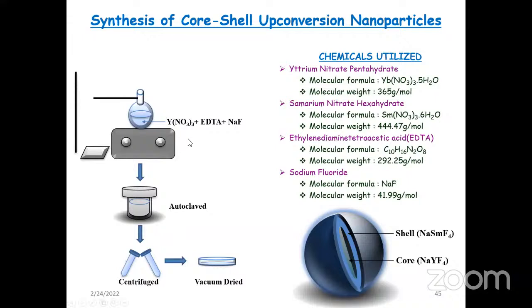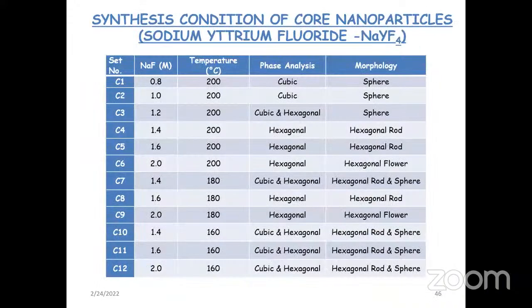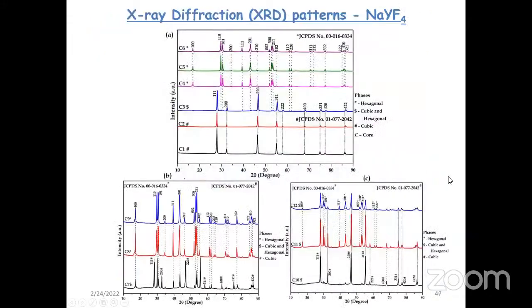Sorry. So we prepared the core nanoparticles by changing the combination of sodium fluoride as well as yttrium nitrate, optimizing the formulation by keeping different temperature conditions of 200 degrees Celsius, 180 and 160, as well as by changing the sodium fluoride concentration, so that we could analyze whether the formed core material has a different morphology as well as phase. It may form as cubic or hexagonal in phase, and morphology-wise it produces spheres, hexagonal rods, or a mixture of hexagonal rods and spheres.